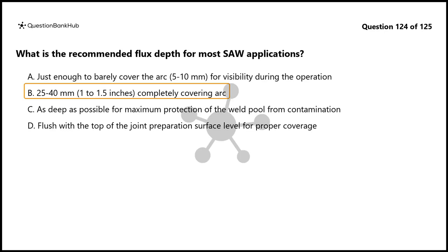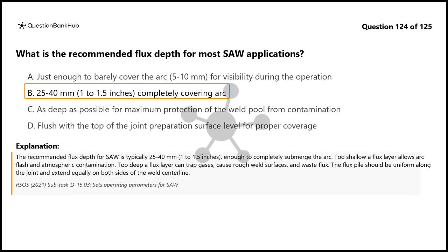The correct answer is B. 25 to 40 mm, 1 to 1.5 inches, completely covering arc. The recommended flux depth for SAW is typically 25 to 40 mm, 1 to 1.5 inches, enough to completely submerge the arc. Too shallow a flux layer allows arc flash and atmospheric contamination.